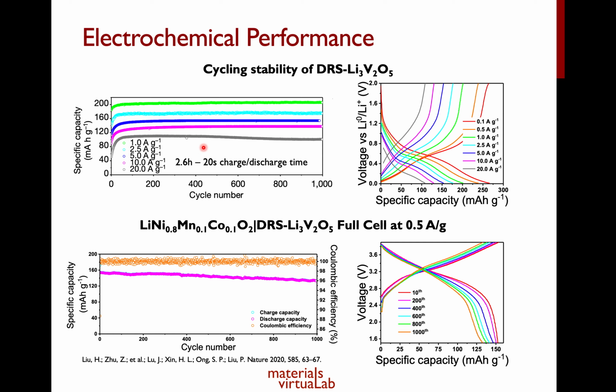So they tested this disordered rock salt insertion anode at charging rates of between 1 ampere per gram to 20 amperes per gram, which corresponds to about 2.6 hours to a 20-second charge or discharge time. And as you can see from these cycling curves, the capacities are extremely stable.